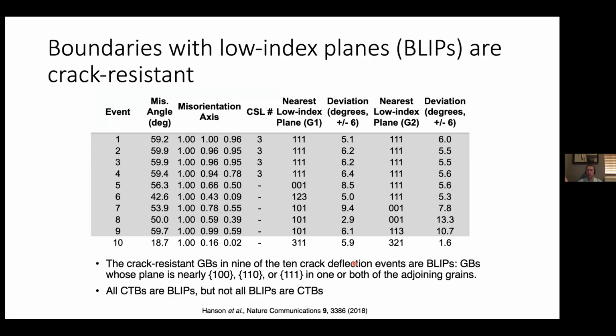And then we looked for commonalities, and we saw that all but one, so 9 out of those 10, of those strong boundaries were occurring along boundaries whose facet planes were of a low Miller index type. By low Miller index, I mean 001, 011, or 111. We call those kinds of boundaries with low index planes, or BLIPs. And all the ones that are shaded gray here, you can see that at least one of the two planes is a low index plane. So all of these have 111 type low index planes. This one has 001, 001.